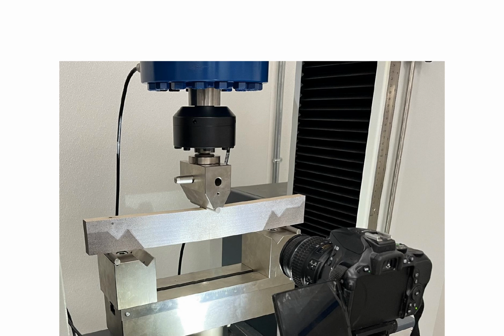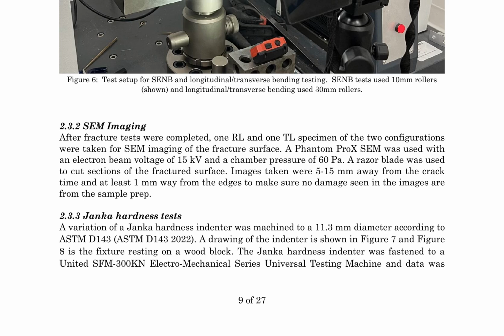Scanning electron microscopy, SEM, imaging was performed on radial-longitudinal, RL, and tangential-longitudinal, TL, specimens from each configuration to examine the fracture surface morphology. A Phantom Pro X SEM was employed, operating at 15 kV and 60 pascals. To ensure accurate imaging, razor-cut sections of the fractured surface were prepared, and images were captured 5 to 15 mm away from the crack tip and at least 1 mm away from the edges to avoid damage from sample preparation.